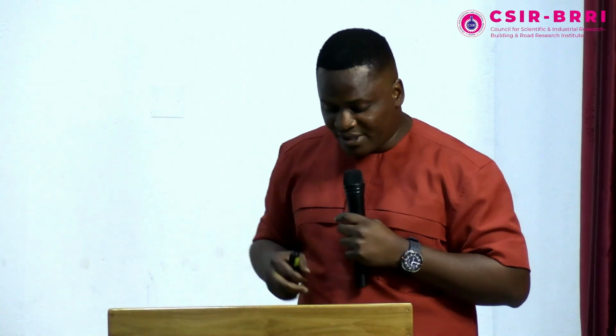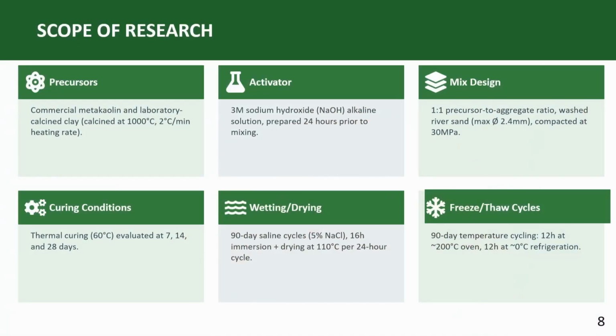Then the last objective is to identify mechanisms governing the durability behavior of calcined clay versus metakaolin geopolymer cement. Okay, so this is going to be the scope of the research. The precursors that are going to be used are metakaolin and calcined clay. So the clay was calcined at a temperature of 1,000 degrees Celsius.